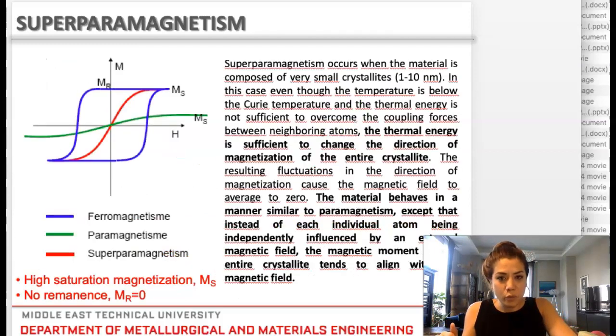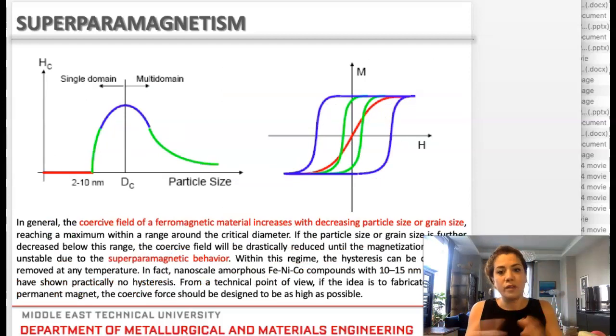These two slides I put up because this is an important phenomenon that is related to the material size, and it will be nice to know. What was paramagnetism? Paramagnetism is when the material overall has magnetic moments, yes, but they're so random under no applied field. What happens to the material? It is not magnetized because overall it's zero, randomly oriented. But once I apply a field, what happens? This red curve here is linear, it doesn't have a hysteresis loop, but it aligns with the magnetic field.